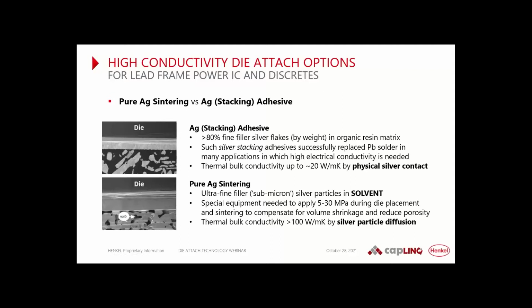And I think in the beginning, let's say, there was pure sintering developed, basically dissolving ultrafine silver particles in a solvent. And then for power modules, that was assembled with force, 5 to 30, at that time certainly 30 megapascal, to suppress the volume shrinkage and the porosity.